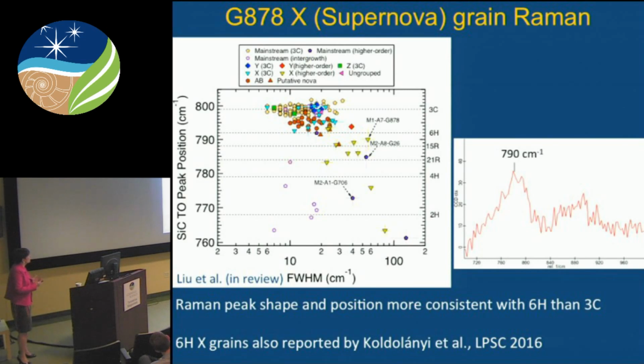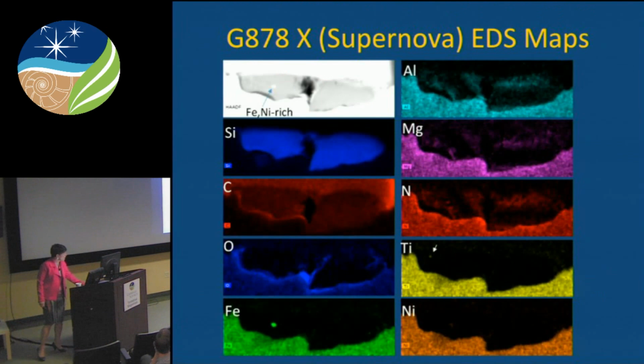So here are the Raman plots of all the grains. We were looking at the 878 grain. It's this one, and here's its TO peak, and you can see that the peak is now asymmetric rather than the triply degenerate 3C type. So this is more consistent with 6H than 3C, and actually in the last year, a group out of Germany, a combination of Münster and Mainz researchers, indicated they also had 6H grains that they knew from the isotopes formed in a supernova.